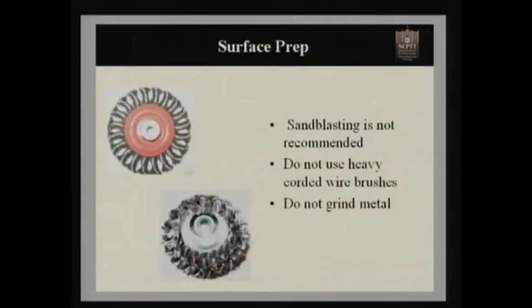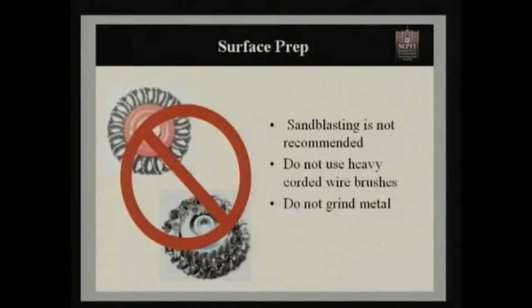smooth out the surface. And if you think about a pitted, rusted surface, a lot of times you have little pits and little valleys, little peaks between them. These heavy corded wire brushes, like we see in the next slide, will actually bend those valleys over, leaving a little pocket of rust below it that can trap water and also leave rust behind. So in our wire brushing, we want to stay with a very fine wire.